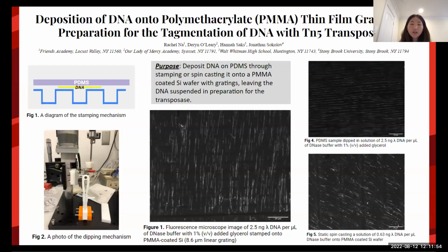For static spin casting, altering the solution incubation times and spin speeds did not have effects on the results. For dynamic drops, a rotation rate of 5,000 RPM showed some bridging, but also caused breakage of the DNA strands as the speed was too fast. Overall, spin casting yielded adequate results shown by figure 5, but they were difficult to replicate. More research is required to find the preferable conditions for spin casting.